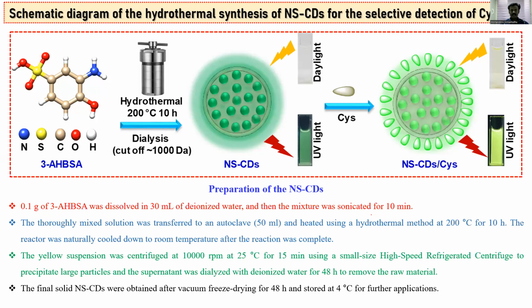It goes into a small-sized high speed centrifuge. We have to precipitate the large particles, and then we can get the supernatant solution. Further, we have to do dialysis. We use a dialysis membrane with deionized water, maximum 24 hours or 48 hours. It depends on the large particles, and it removes the raw materials also.